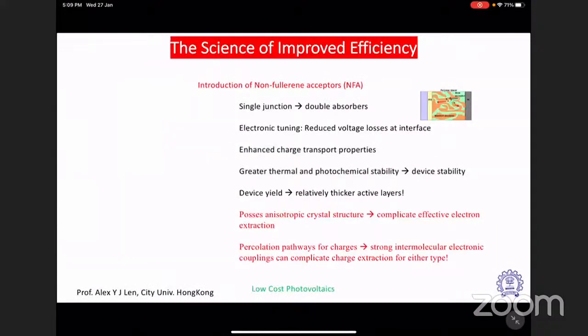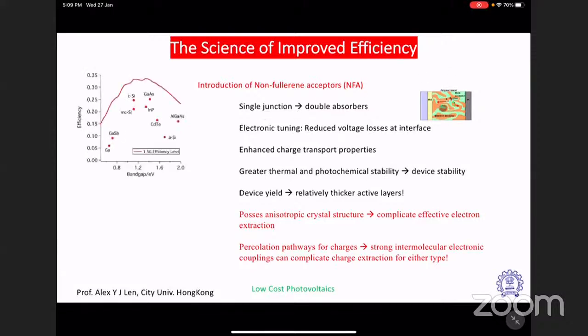So that was for the fullerene case, but when we introduce the non-fullerene, it gives an idea about a single junction with double absorber. So I had this orange and the green, but the fullerene does not absorb much light. But now I'm using some of the non-fullerene acceptors, which have an electronic band gap even lower than the donor system. So I'm not limited by this Shockley limit, because these all are for the single absorber. Now I have the double absorber in the same cell.